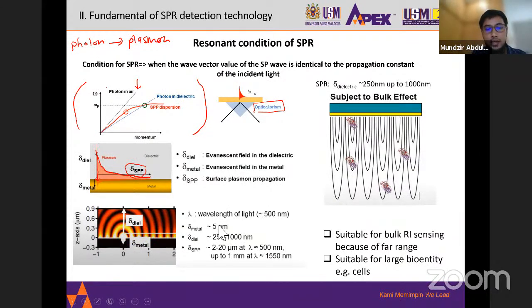All right, so let's consider the wavelength of light that we introduce to the metal surface is 500 nanometer, and the evanescent wave into the metal is very short, just 5 nanometer, because we know metal has a very high refractive index, so the penetration is very low. The penetration depth into the dielectric is very large, very long, right? 250 up to 1 micron. So our metal surface can sense whatever dielectric material we have from 250 nanometer up to 1000 nanometer. It depends on the wavelength and the type of metal and so on.